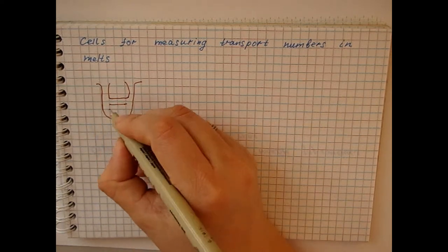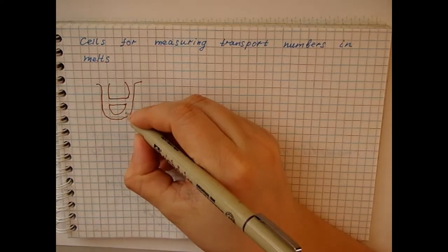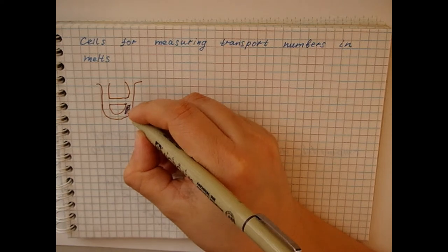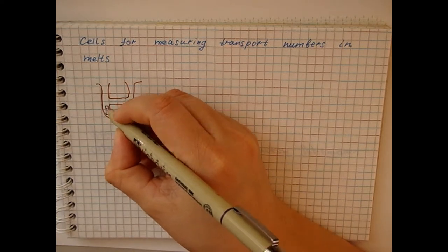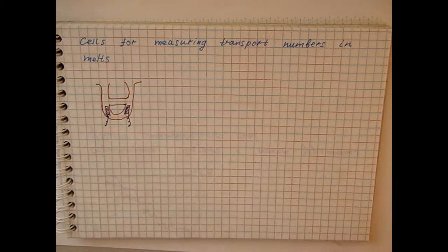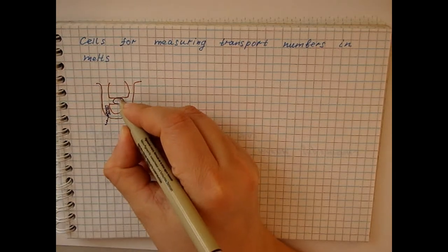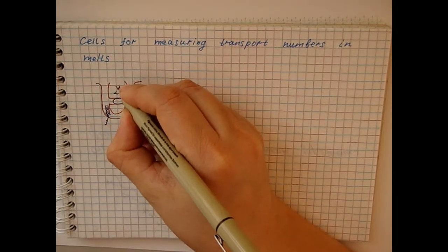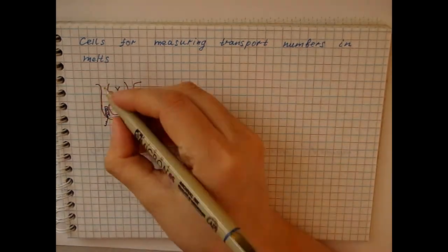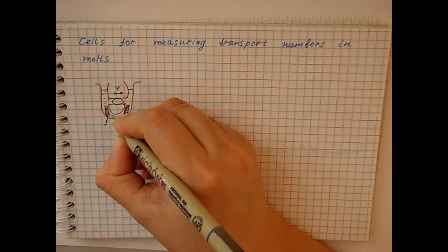Liquid overflow is possible through a capillary in which an air bubble is placed. Since the bubble moves under the action of a small force, liquid overflow through the membrane is completely excluded. Transport numbers are calculated from the speed at which the bubble moves.